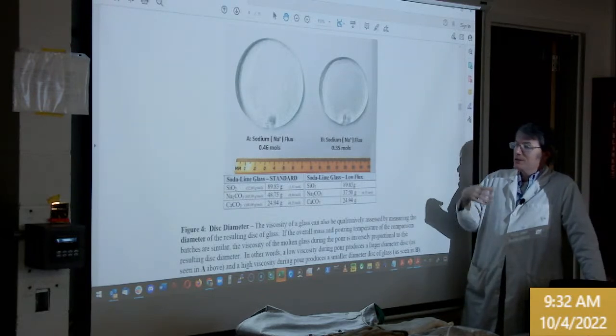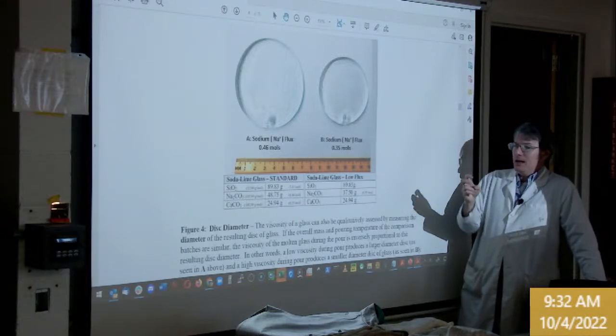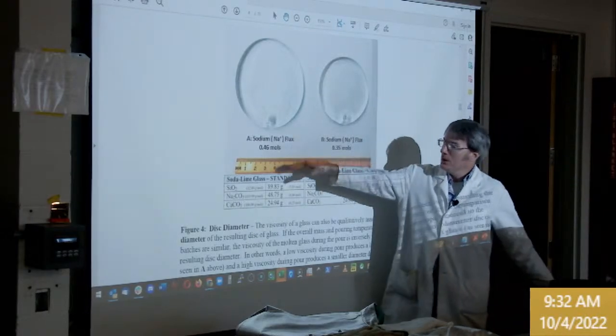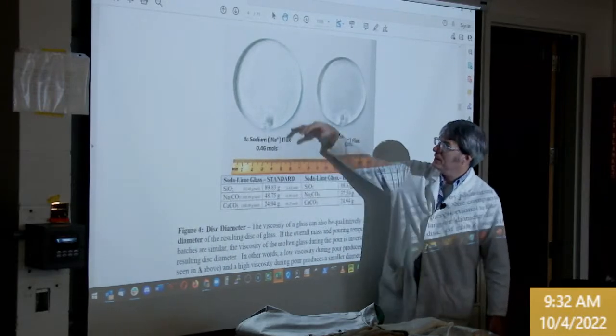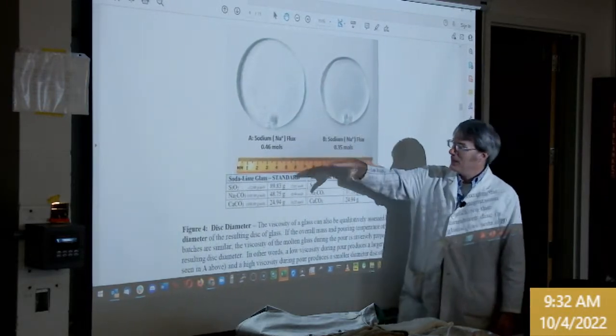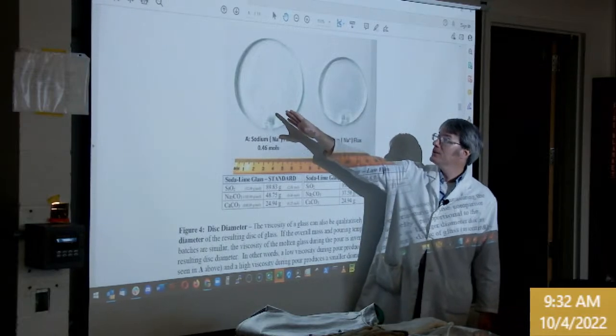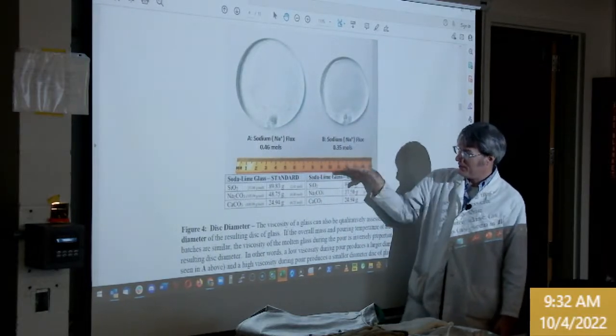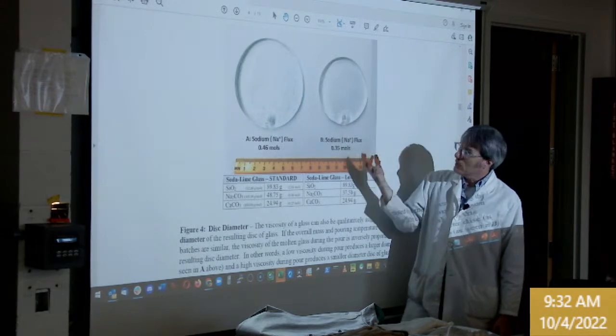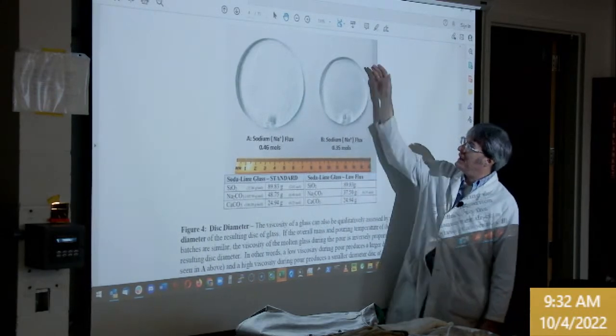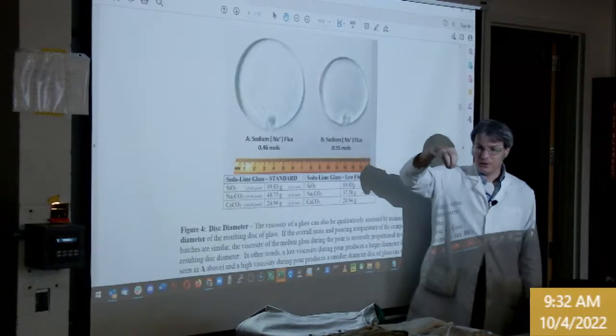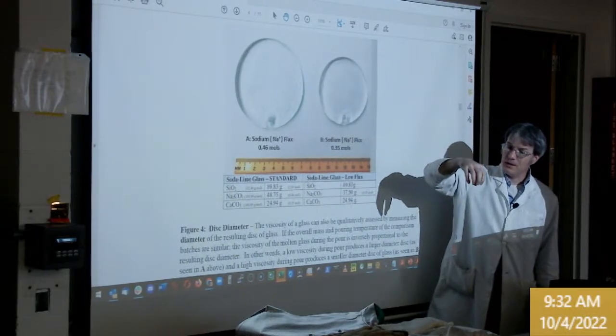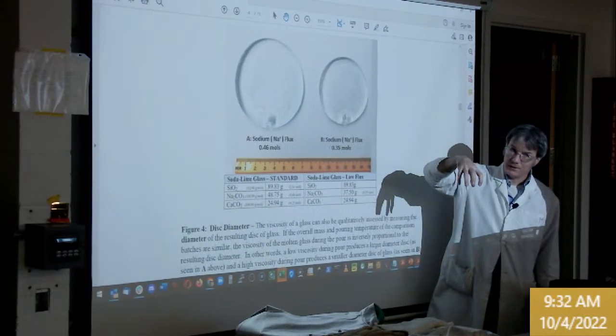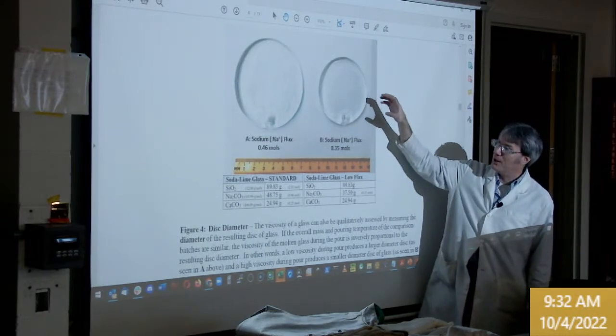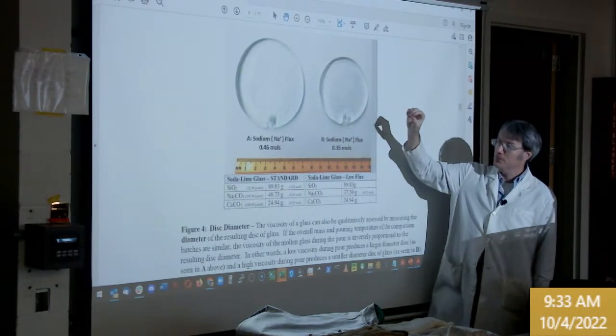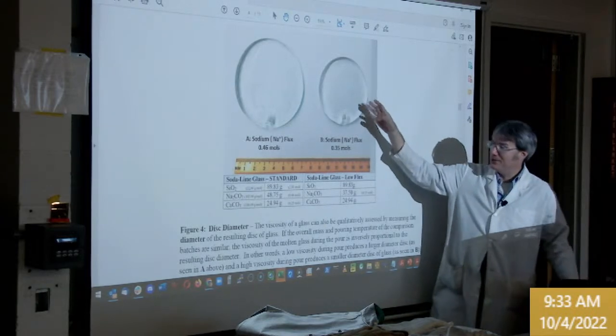So for the questions that ask about the standard sodium glass, well, that's this one. And you can see the approximate size and diameter. And so this was a high flux, this was a low flux with everything else held the same. Okay, we can see some differences here. The diameter is smaller. That means that during the pour, it didn't spread as easily, higher viscosity, and I probably didn't recover quite as much from the crucible. Another fingerprint of high viscosity.